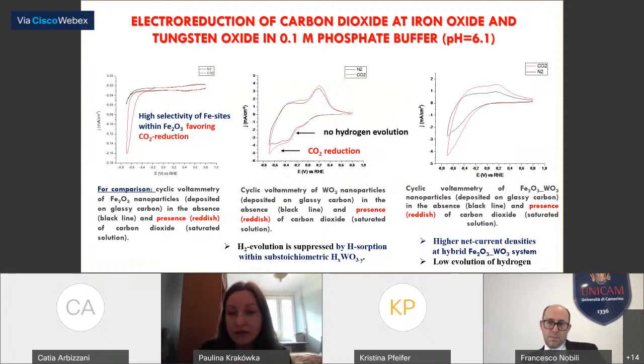And here we also can see that for a two-layer system, we will observe the reduction process at more positive potential. We get higher net current density, and thanks to substoichiometric H-sorption by tungsten oxide structure, we have low evolution of hydrogen.